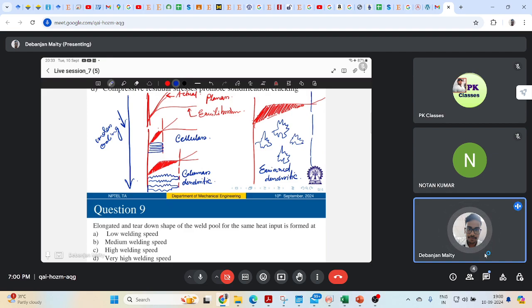Can you tell me the region where dendrites, both columnar or equiaxed, and the liquid phase coexist, what is it known as? It is known as the mushy zone, where liquid and solid coexist. So at a very high degree of supercooling or undercooling, whatever you call it, the mushy zone can become so wide that it is easier for equiaxed dendrites to nucleate than for columnar dendrites to stretch all the way across the mushy zone, right?